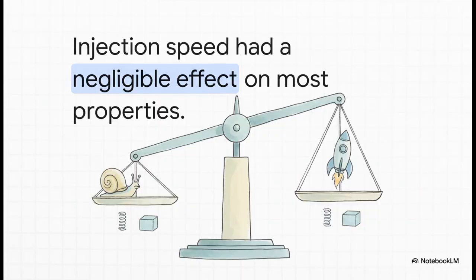But here's the twist. Even though the mixing looked better, it didn't actually matter when it came to performance. The researchers found that for almost all of the important properties, toughness, stiffness, strength, the injection speed had pretty much no effect. It was a wash.